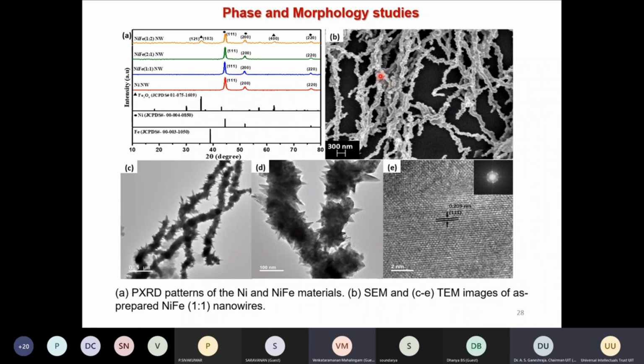What we see in the SEM images is basically beautiful nanowires with some protrusions on the surface, which is very clear from the TEM images. You can see some kind of protrusions at the surface. This is the first time we are observing something interesting on the surface.